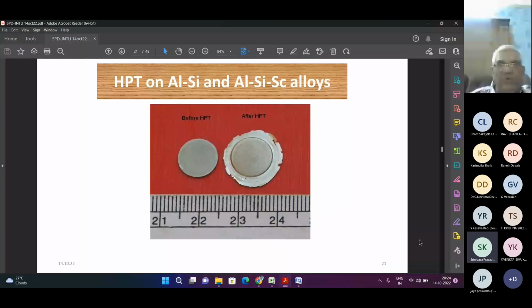So we applied for this, and we showed very nicely that by using this HPT process, whatever material you are talking about, aluminum silicon or aluminum magnesium or aluminum magnesium scandium alloy, we can achieve mechanical properties of 1000 MPa yield strength. But the question asked was, when the sample is only 10 diameter and 1 thickness, where are you going to use it in aerospace?